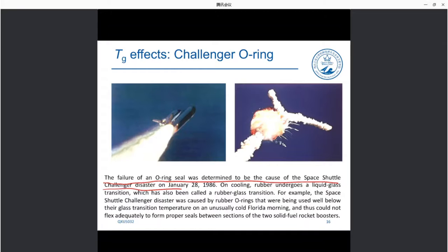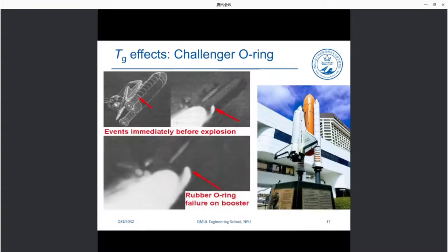So essentially, it did not display the seal. In order to have sealing characteristics, we need elastomeric properties. But because it was so cold, the O-ring was displaying glassy properties. Okay, stiff properties, stiff modulus. Yeah, so that's where it happened, and a failure took place here.